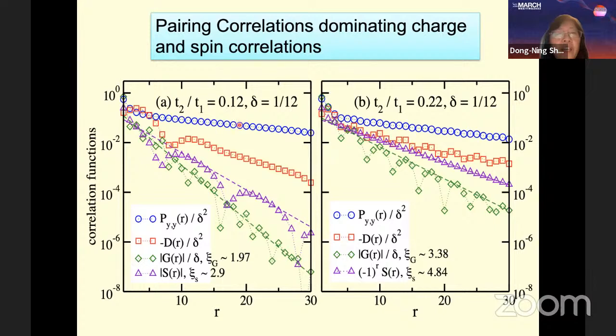Now we compare this pairing correlation with other correlations. We changed the scale of those correlations because the pairing is always proportional to delta square. If we renormalize it with delta square, then those correlations have a value around 1 at short distance. We did a similar rescale for the Green's function and the spin correlation, so they are all in the same order at short distance.